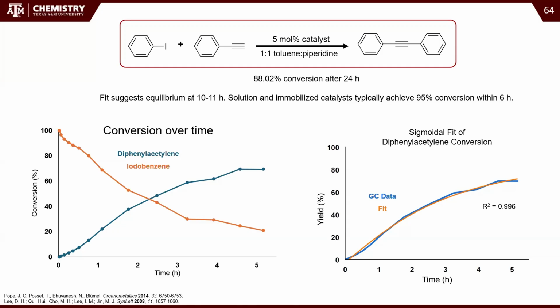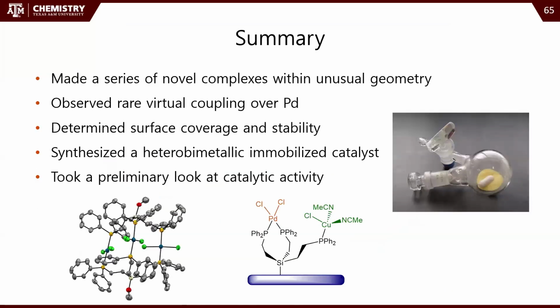And from that, I modeled that we should have reached equilibrium about 10 or 11 hours in. And if we look in the literature, a lot of other catalysts will achieve pretty much stoichiometric conversion within about 6 hours. So not a ground-breaking catalyst, but I've also run this twice with the same material. So it could just need more tinkering to really work. But so far it seems a little iffy. But we got catalysis going, and it seems like it's working, at least as a catalyst. So that was nice and reassuring.